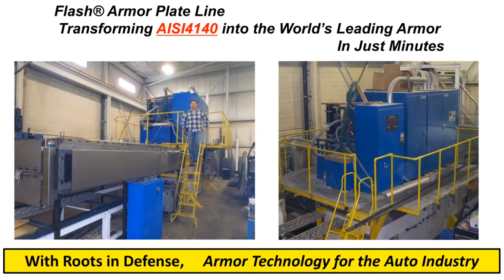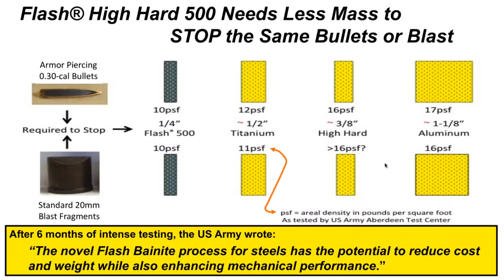Now, how good is flash bainite armor? A few years ago, we were doing work with Army Research Lab, and we were making high hard 500 Brinell armor. What we were doing was taking 30 caliber armor piercing bullets at a given velocity and 20 millimeter blast fragments at a specific velocity. And the Army tested and found out what 10 pounds per square foot, or 10 PSF, of our quarter inch flash 500 plate could stop.